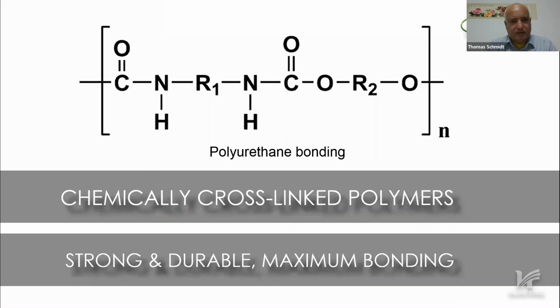And I continue. This ink formulation, like Covestro already has shown, is a chemically cross-linked polymer. So we use chemical hardeners to cross-link the resin structures, and this results in a very strong and durable coating. And we can also achieve maximum bonding strength to various types of textile fibers. Basically, it is all based on polyurethane chemistry.